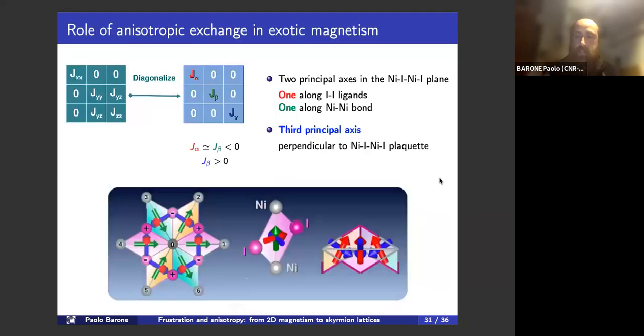Now we can wonder what is the role of the anisotropic exchange in this particularly exotic magnetic phase. To understand that, it's better to visualize the principal axes of the anisotropic exchange. We found that there are 2 almost degenerate eigenvalues, corresponding to principal axes which lie in the plane of the plaquette formed by the nickel-iodine atoms, and which are negative in sign. And then there is a third, positive eigenvalue, corresponding instead to a principal axis which is perpendicular to the plaquette.